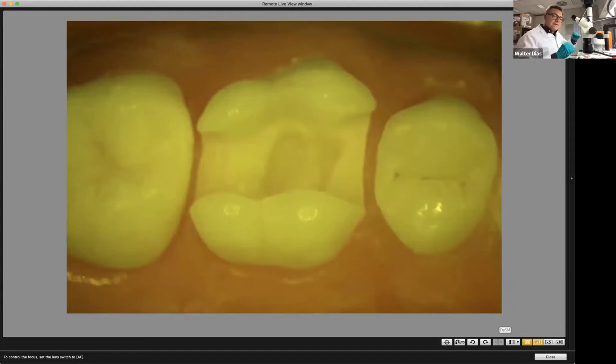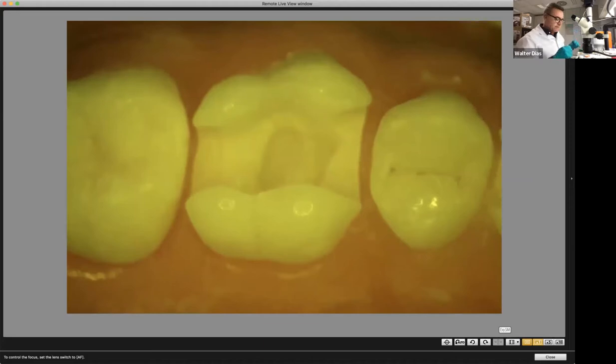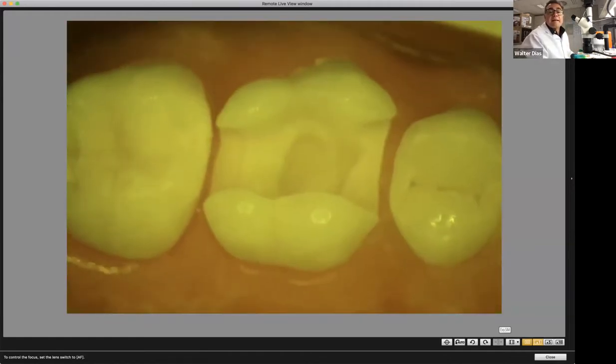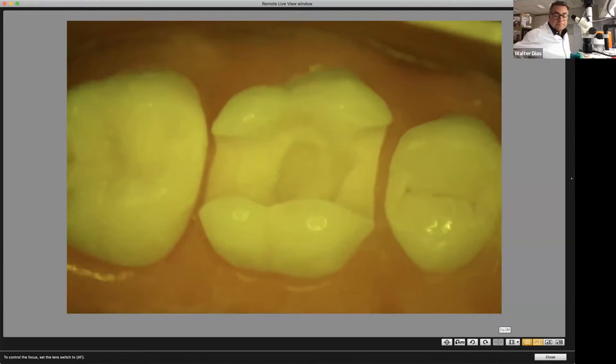So self-cure is higher than dual cure, and pure light cure is higher than dual cure. Is that correct? Does it make sense? Yeah? So the best one is direct light curing, as when you do immediate dentinal sealing with SDR, yeah? That's the best one. The second one is when you do a dual cure system in self-cure mode, which is what we're gonna do now. And then the third one is dual cure when you light cure the cement, okay?